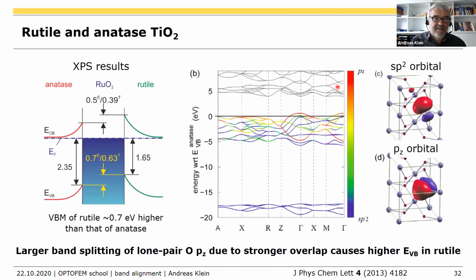So what about the titanium dioxide? This was our measurement. We did, again, interfaces with ruthenium oxide and ITO. And we find that the anatase is about 0.7 eV lower than the rutile. We got some theory which showed exactly the same thing. So this is both titanium dioxide, anatase and rutile, in principle a different polytype.